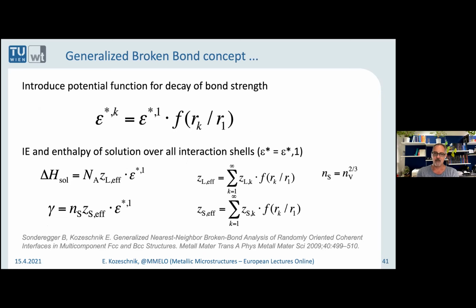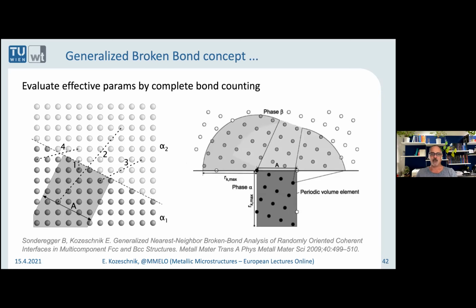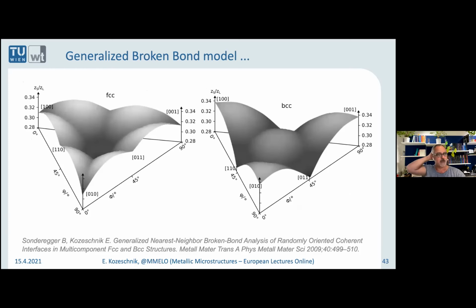And with that, we could find some convergence. When you integrate that over 500 nearest neighbor shells, then you converge. And by that, we could also show that it's necessary to take into account farther interactions. And the result was that for different directions, we got a structural factor that was in the vicinity of 0.32 for FCC, for BCC.